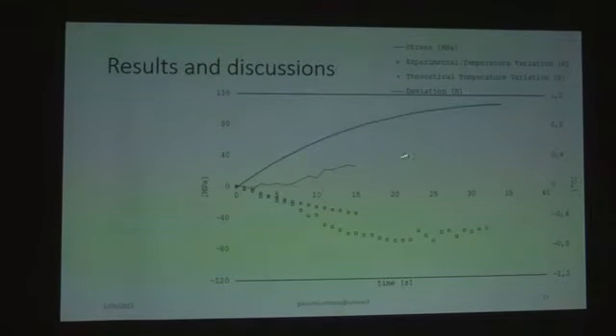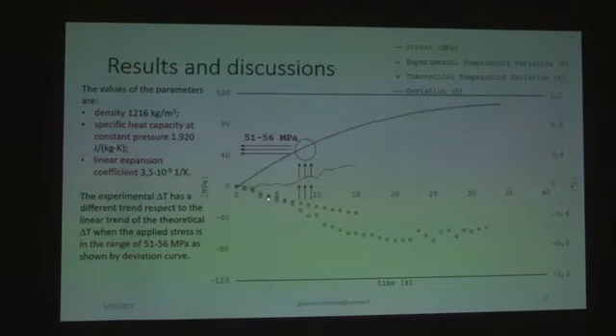Okay, this is an interesting slide. In blue you have the stress curve versus the time, and in green square you can see the surface temperature variation detected by the camera. The red circles are the theoretical temperature variation by the thermoelastic equation, by these parameters. The black line is the deviation of experimental temperature variation from theoretical temperature variation, and you can see that there is a difference for a stress of about 56 megapascal. Remember these values.